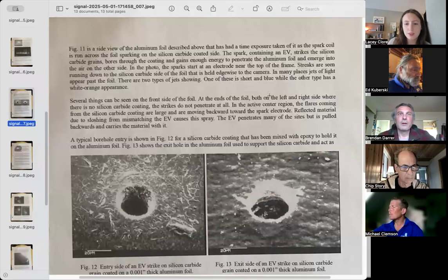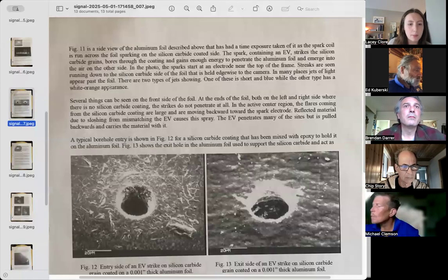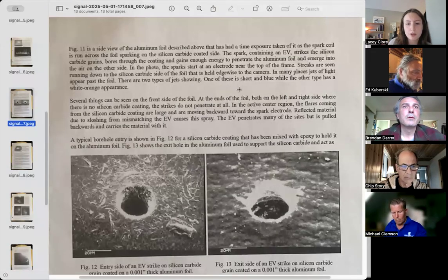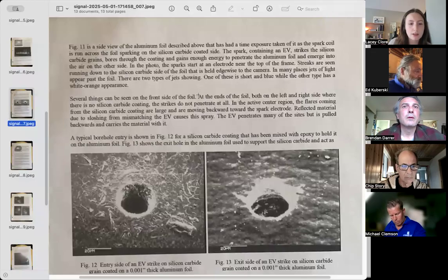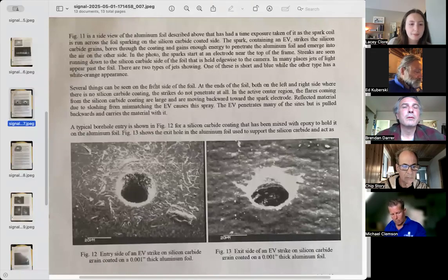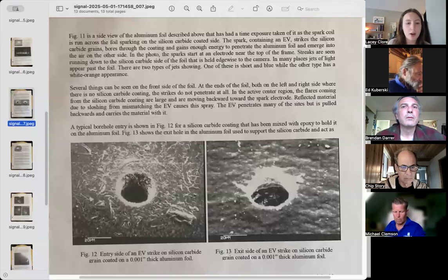In many places, jets of light appear past the foil. There are two types of jets showing. One of these is short and blue, while the other type has a white-orange appearance. Several things can be seen on the front side of the foil. At the ends of the foil, both on the left and right side where there is no silicon carbide coating, the strikes do not penetrate at all.